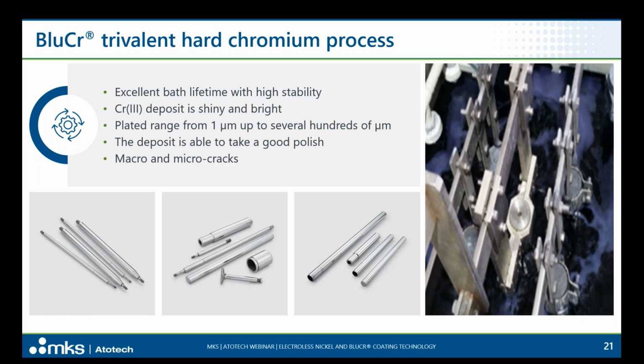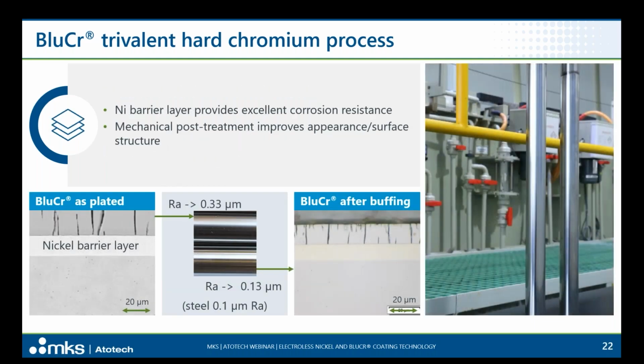Yes, on the bottom part of the slide, you can see the parts plated with trivalent chrome. You can clearly see that the deposit is very shiny, it's very bright. We can plate starting from very low thicknesses, from several micrometers for several applications, and end up with several hundreds of micrometers or even more. It depends on the applications, but we are able with our process to plate with interruptions, with some grinding steps in between. This is possible. And last but not least, the deposit has macro and micro cracks. And what does it mean? Let's look at the next slide.